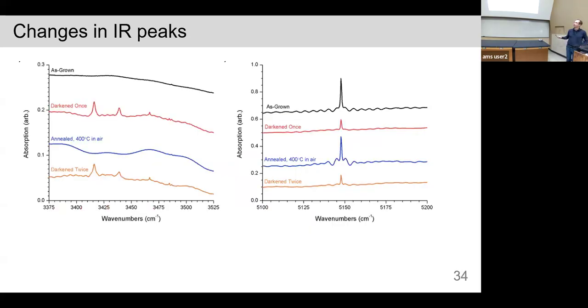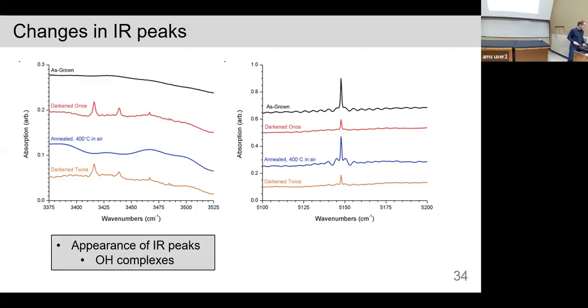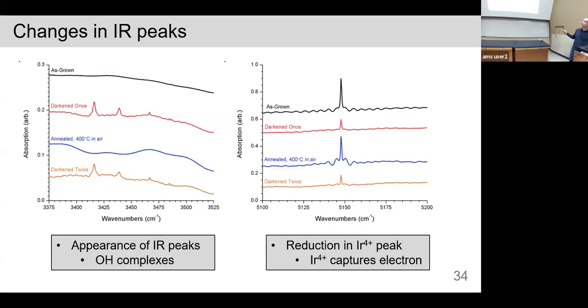And so I'll show you these peaks. Again, as grown. We darken it once, we get these hydrogen modes. We anneal it at 400 degrees in air, that's just on a hot plate, and it erases everything. Then we try it again. And so we darken it again, and those peaks reappear. So the appearance of IR peaks says we're forming these OH bonds in the crystal. Now the iridium is telling us something else. So the iridium peak, this is due to the iridium 4+. When we darken, it actually decreases in intensity. So we think iridium 4+ captures an electron, turning it into 3+, which is invisible. You repeat the experiment, it comes back when you anneal, and then darken again, and it decreases again.